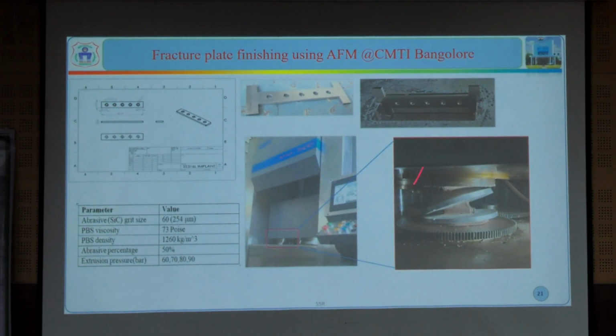Some basic study we have done on a design fracture plate. You can see here, this is a design fracture plate and this is an original fracture plate, and we have not used our machine here because our machine was under fabrication during the study. So we used a machine available at CMTI Bangalore, for abrasive flow machining. They pumped the media to and fro on a sample, and these are the parameters we used in the study, like the abrasive grit size and the viscosity, and you can see the density, abrasive percentage, pressure, etc. varied.